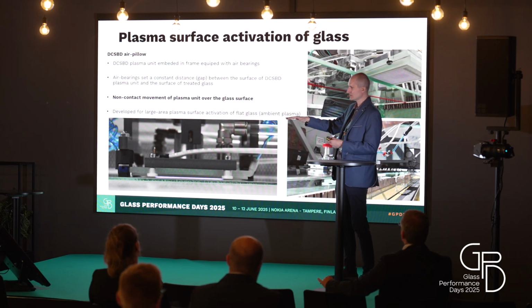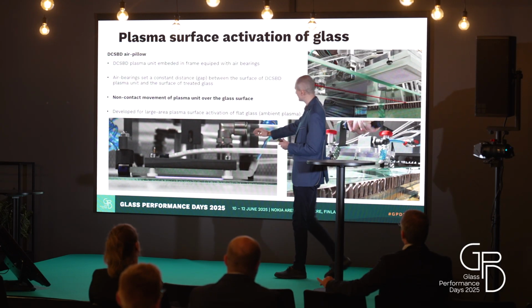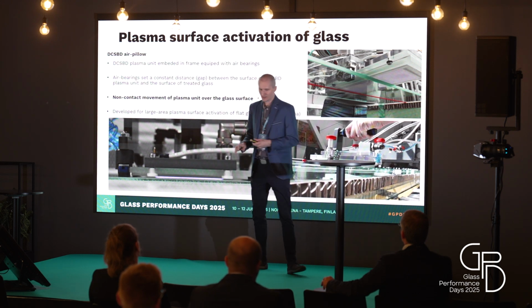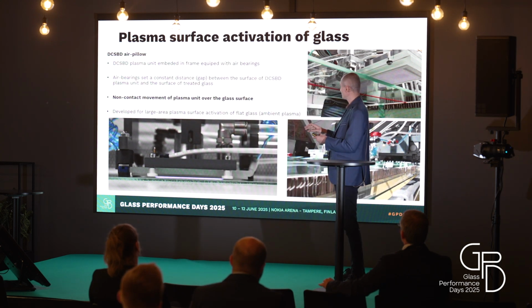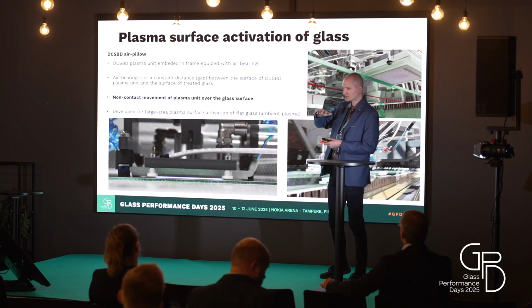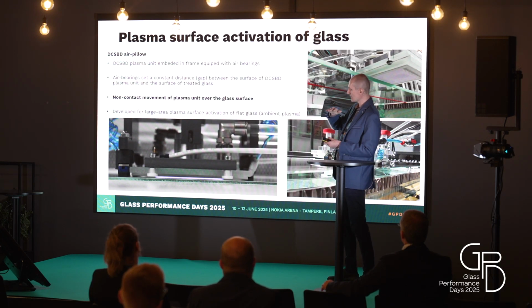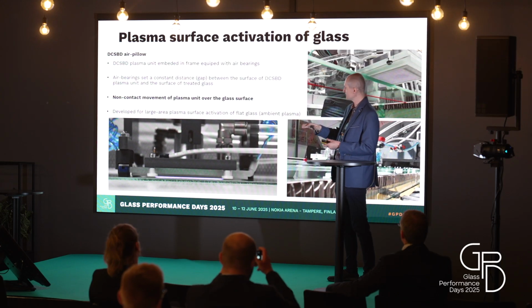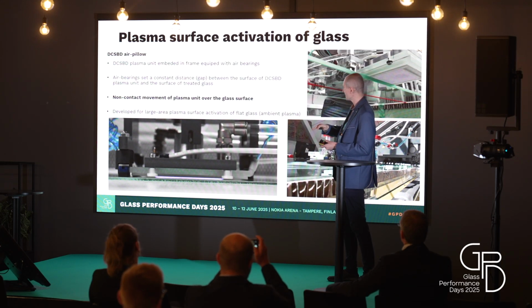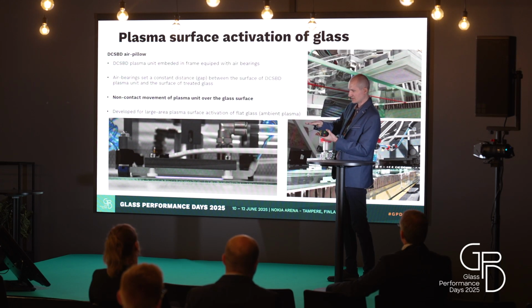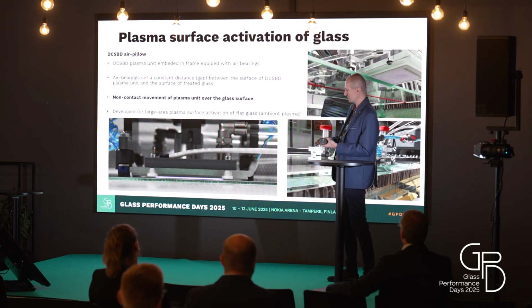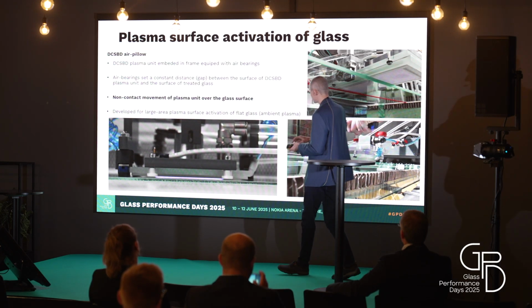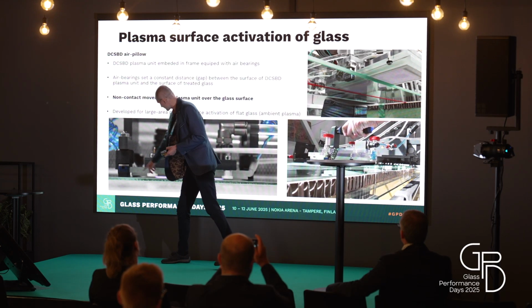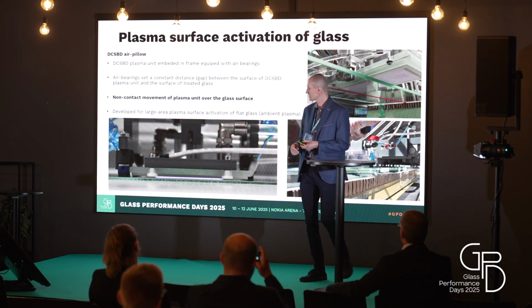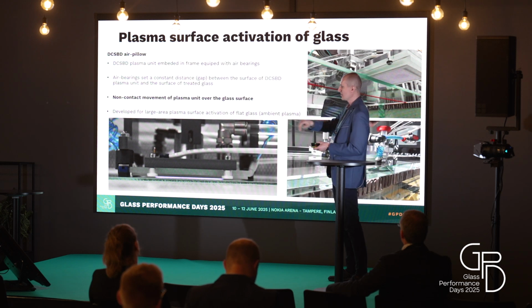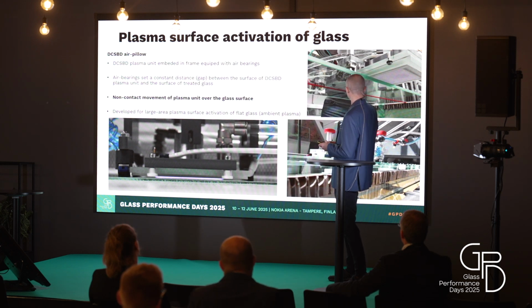Since in this configuration this plasma is generated as a thin layer, as we can see here, we developed a special unit, a special tool, using which our plasma unit is kept at a constant, very precise distance over the flat glass without any direct contact with the glass surface to remove any contamination, for example. We are using a system of air bearings like we have it here. And using this system, we can move over the surface without any friction, without any damaging of the glass.